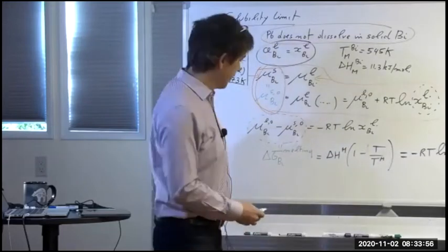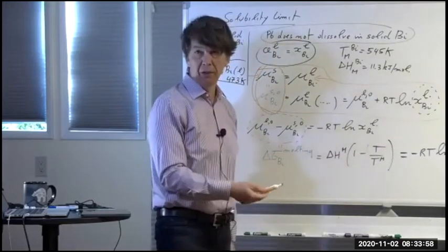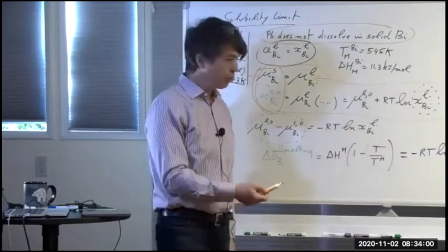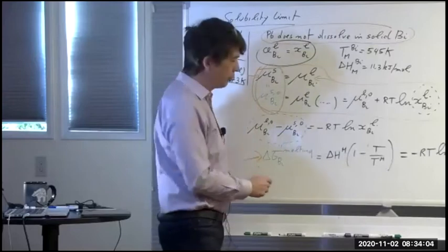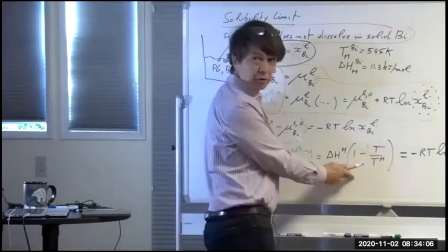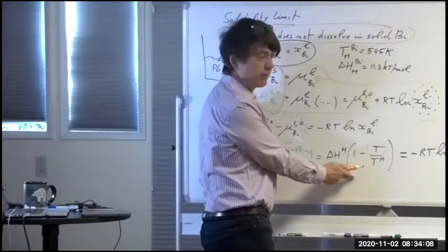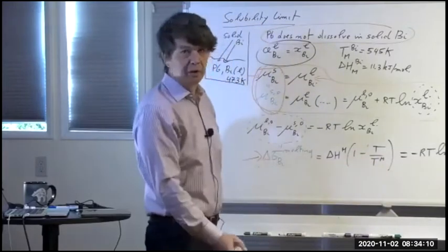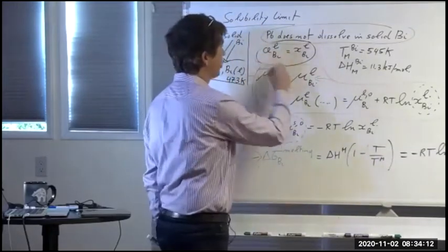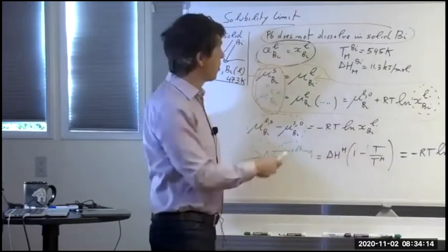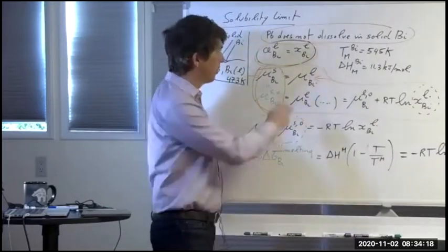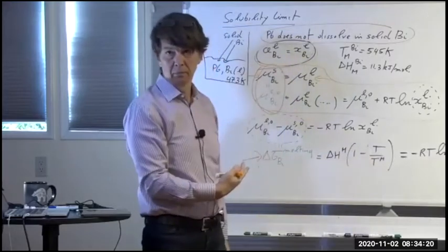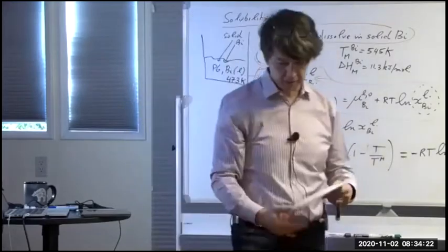If you had heat capacities for the liquid and the solid state, you could make this better, because you could make this a more complicated function of T, right? But the most serious approximation is probably this, and we'll talk a lot more about this. This is a remarkable statement, right? Saying that the activity only depends on the dilution. That's really the statement that is made here.